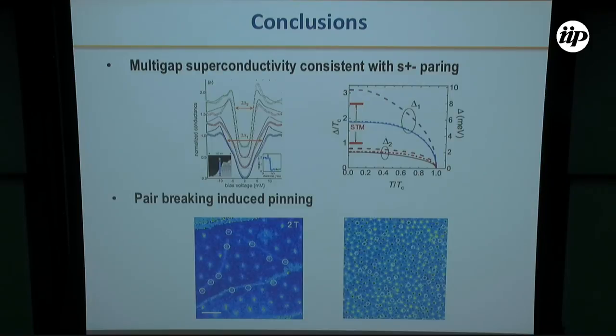Just to finish, I conclude. In this stoichiometric material with very high Tc, we have found multi-gap superconductivity, which is consistent with S plus minus pairing. And we have found that the main contribution to the intrinsic pinning in this material, in the absence of substitutional disorder, is the pair breaking defects.